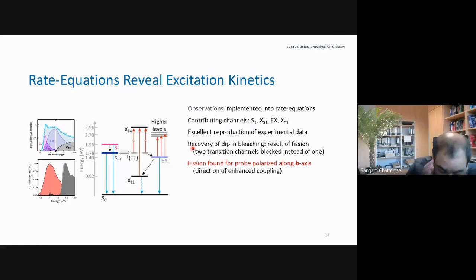And putting all of this together, we came up with a rate equation model, which we confirmed with DFT-based microscopic calculation, which let us understand the kinetics of the system, where we have fast relaxation in the singlet state. We have an interplay with the triplets, and the triplet pair states, which are correlated entities which need to form and need to diffuse, and that they can do before they actually form the incoherent triplet excitons, can do either via an excimer state, which is a correlated singlet type state, or via direct diffusion of the excitons and then give induced absorption signatures, which are predominantly along the B axis. And that basically means that, okay, if you have coupling between the molecules, a process which requires coupling between the molecules is more efficient. Not too surprising, but a good message in the end.